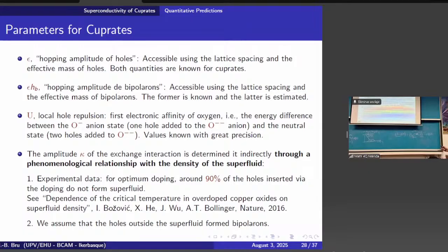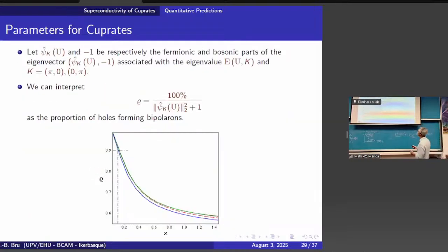The amplitude K of the exchange interaction is the most difficult to fix. We fix it by knowing that there is a paper in Nature in 2016 which says that 90% of the charge carriers of the hole doping do not participate in the conduction. That means they are bipolarons. So we run our model in such a way that, you look at the proportion of bipolarons, 1 divided by the full norm. You think that it should be 90%. That gives you a certain number, and you look if it's coherent. Of course, if you find, I don't know, 1 billion electron volts, and the other one has 1 electron volt, you say there is something bizarre here.